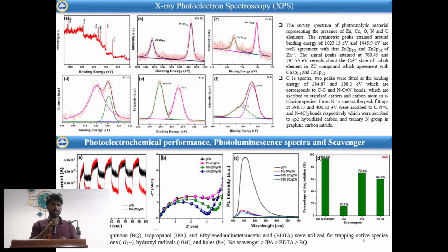And we have also calculated the XPS analysis, through which we have confirmed the presence of all the elements which we have used in the composite sample. So this particular XPS was taken for the highest dopant sample, which is 15% zinc cobalt oxide with graphitic carbon nitride. And we have taken photoelectrochemical analysis and impedance analysis for the charge transfer properties.